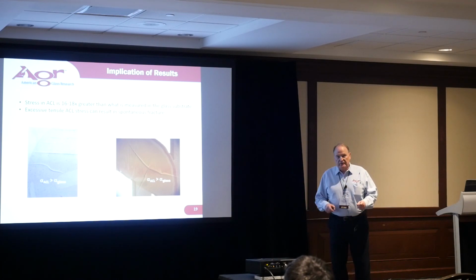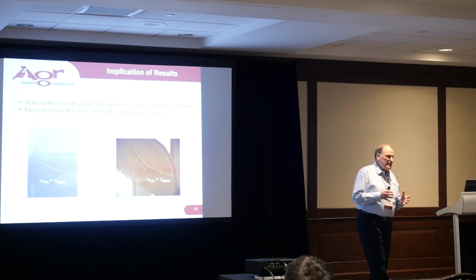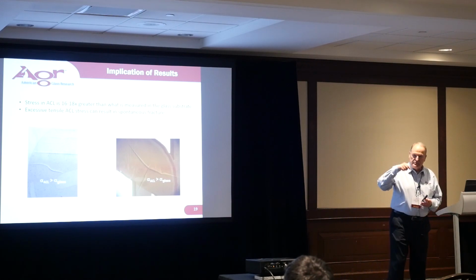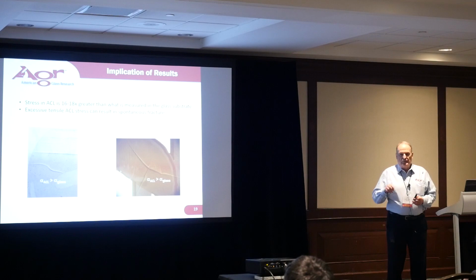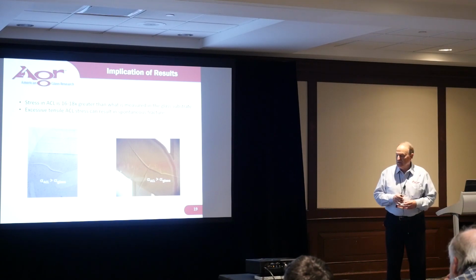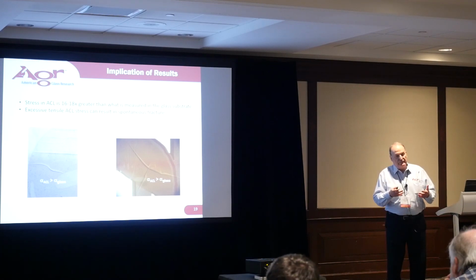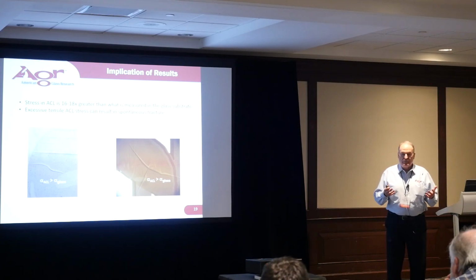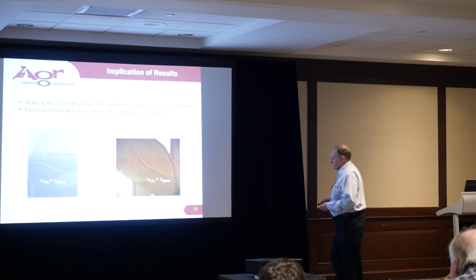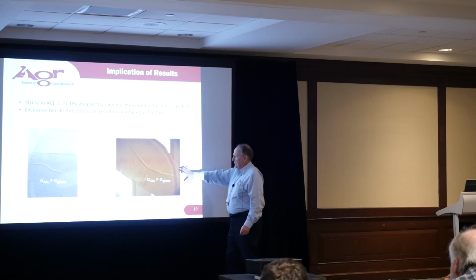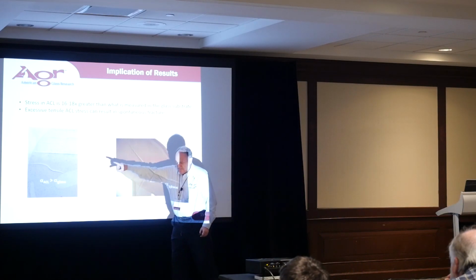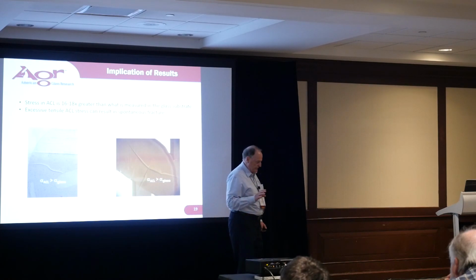These micro cracks are very hard, probably impossible to see if you're looking at the outside surface. But if you take a segment out of the glass and look at it from the inside surface, and you get the light right, you can see them very easily. Now, these are two different examples, one here, one there, both showing the same effect.